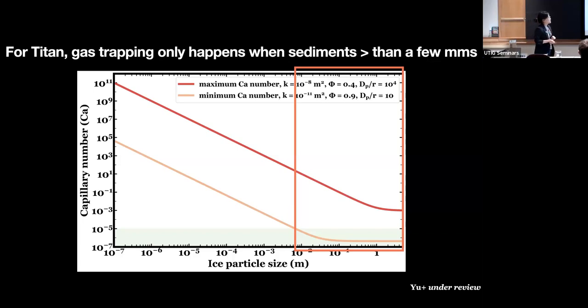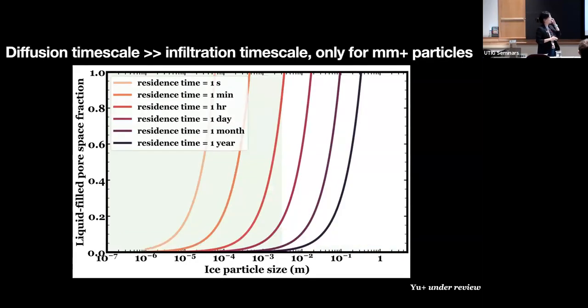Okay. And then we plotted, if we assume gas trapping, and the diffusion timescale dominates the timescale of the flotation, how long would it take for things to float? They increase the timescale by orders of magnitude compared to the infiltration theory. And we can actually have particles float for days and months, not so much years, I would say. So, the right kind of timescale.